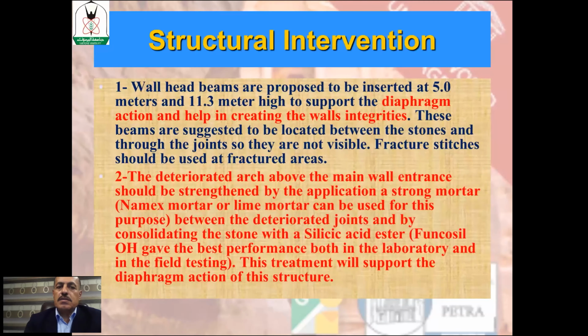So that's why we suggested wall head beams to be inserted at a certain height and to support the diaphragm actions and help in creating the wall integrities. Also, the deteriorated arch above the main wall entrance should be strengthened by the application of a stronger mortar, Namex or lime mortar based on our results between the deteriorated joints, and by consolidating the stone with the silicic acid esters, Funcosil OH, which gave the best performance both in the laboratory and in the field testing program.